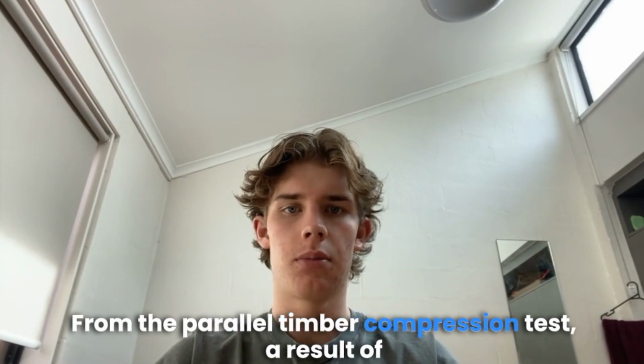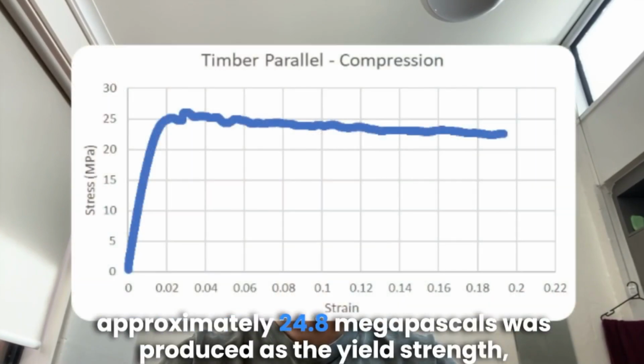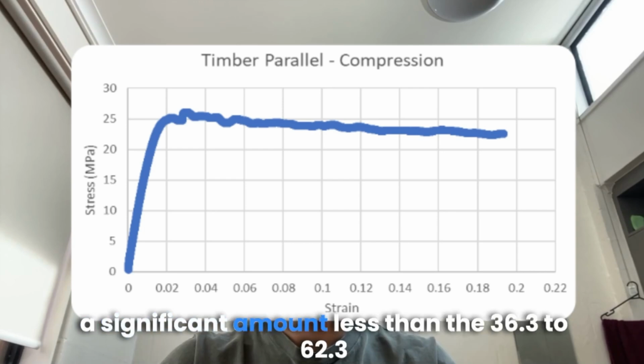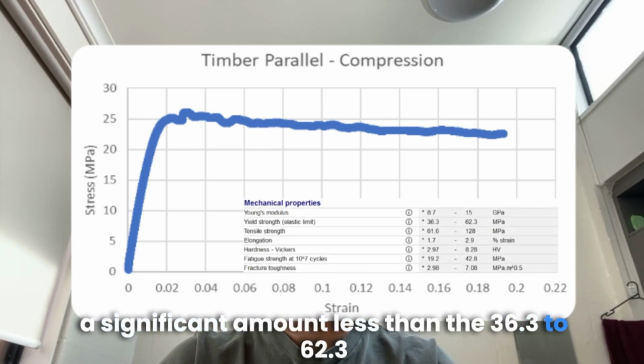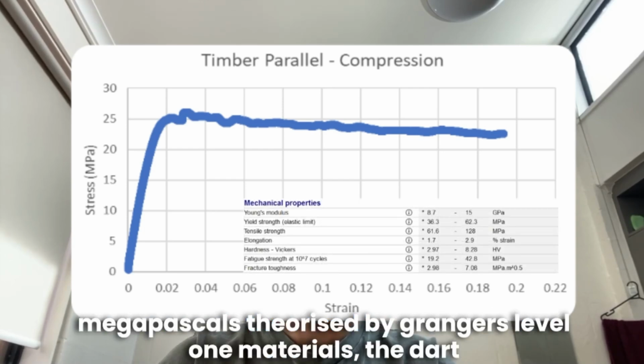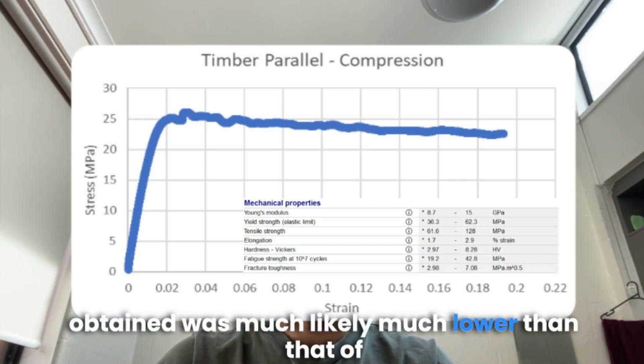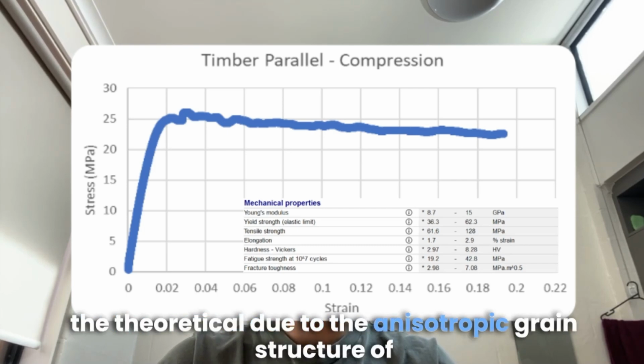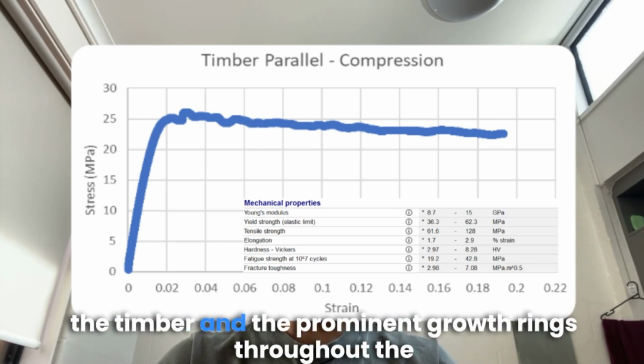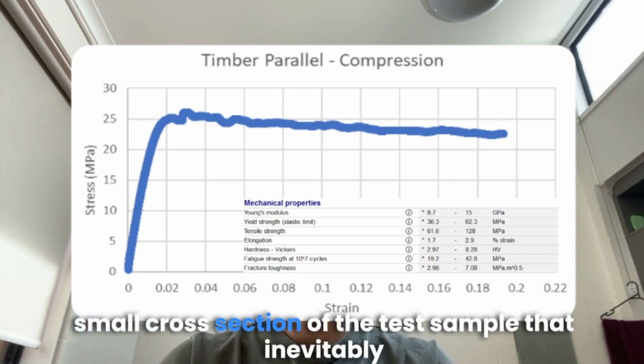From the parallel timber compression test, a result of approximately 24.8 megapascals was produced as the yield strength, a significant amount less than the 36.3 to 62.3 megapascals theorized by Granta's Level 1 materials. The data obtained was likely much lower than that of the theoretical, due to the anisotropic grain structure of the timber and the prominent growth rings throughout the small cross-section of the test sample that inevitably induced the natural failure.